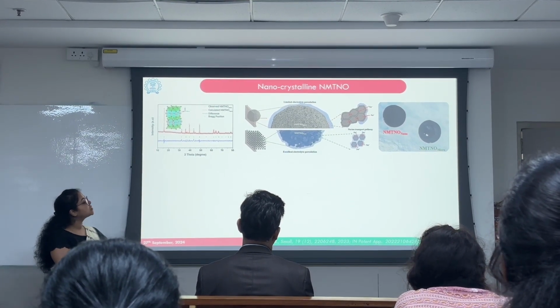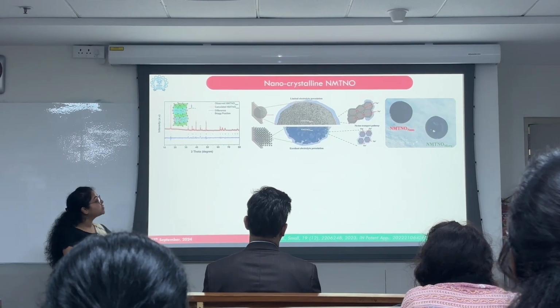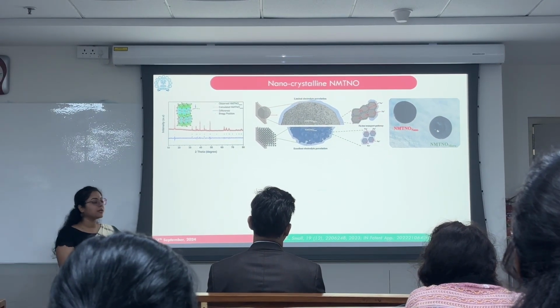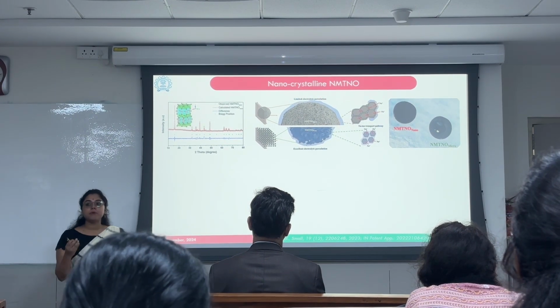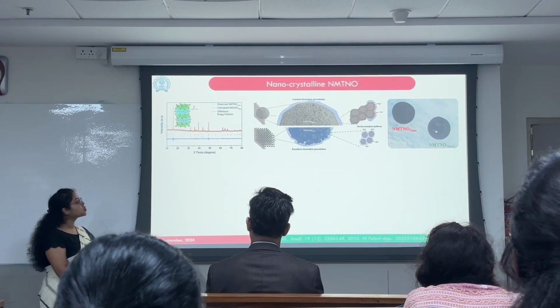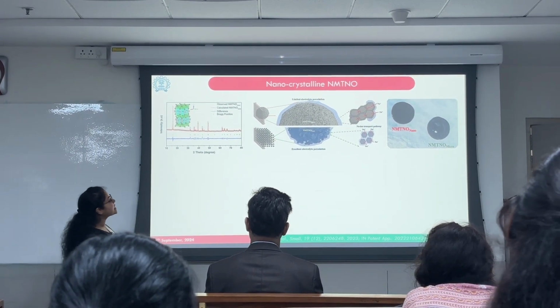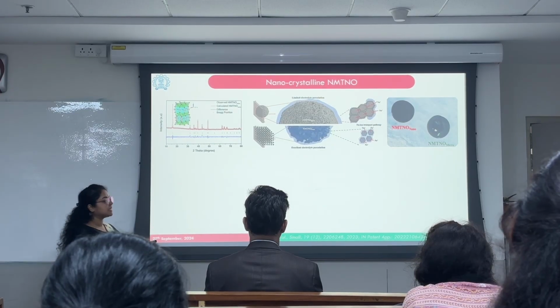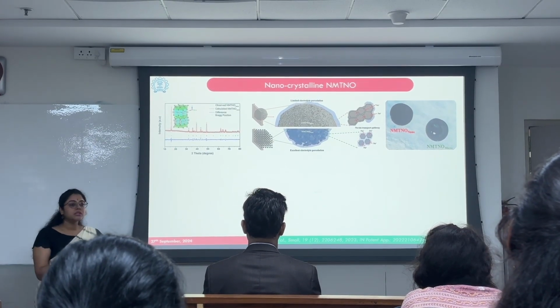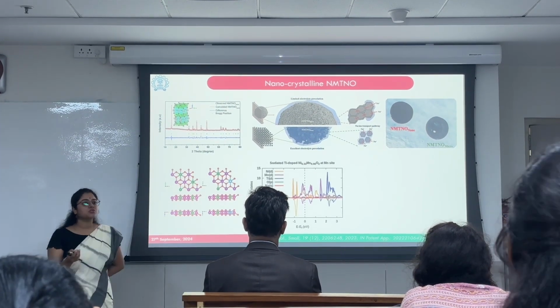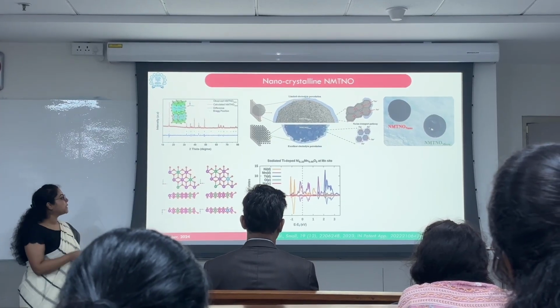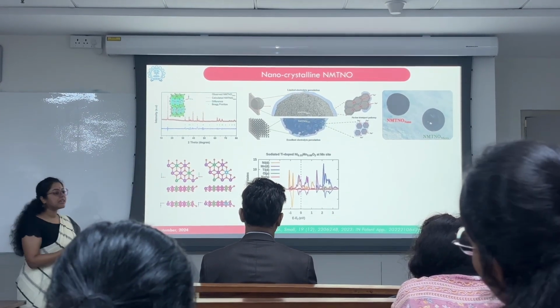Thus, we validated it through an experiment of contact angle measurement, and through this optical image, we can see that for the same amount of time, when we drop the same amount of electrolyte on both the NMTNO nano and micro electrodes, the nano absorbed the electrolyte easily, whereas the NMTNO micro still contains the bubble.